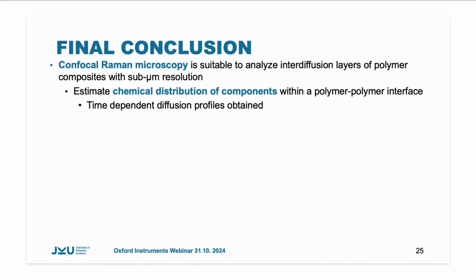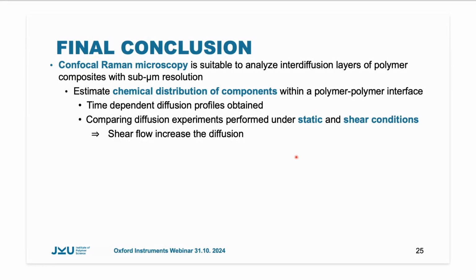I hope I could show you that confocal Raman microscopy is a suitable tool to analyze the interdiffusion layers of polymer composites. We could estimate chemical distribution of the components within the polymer-polymer interface so that time-dependent diffusion profiles can be obtained, which proves that we have Fickian diffusion. When we compare diffusion experiments performed under static and shear conditions, we see that shear flow increases diffusion, but we have also to take into account that chain orientation can have an impact on the interdiffusion layer thickness.